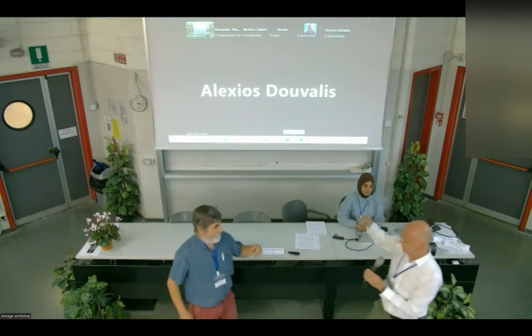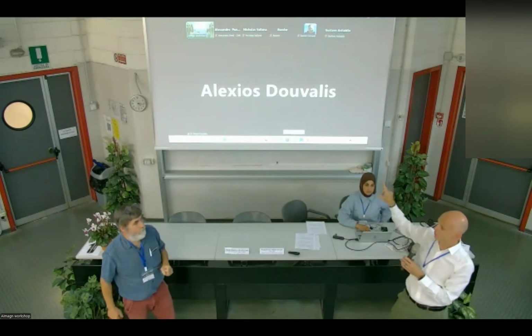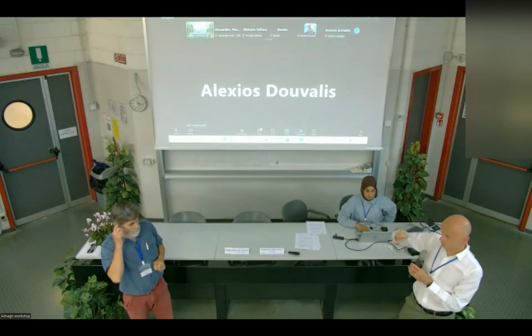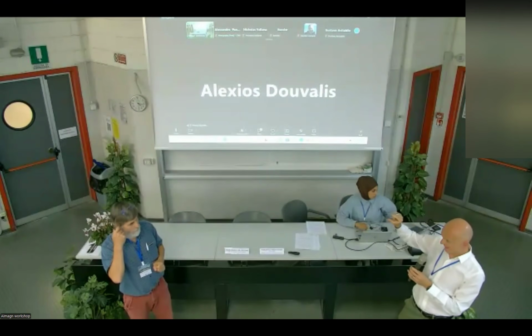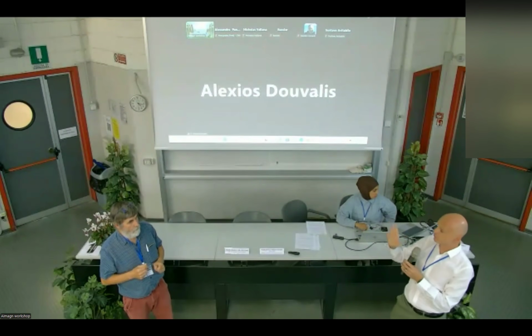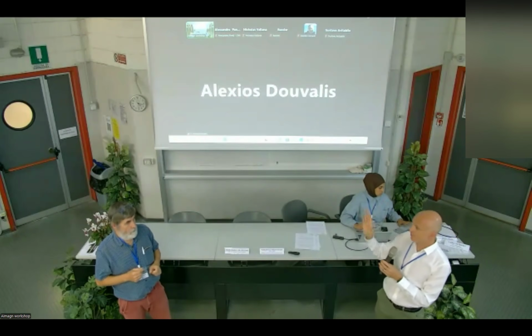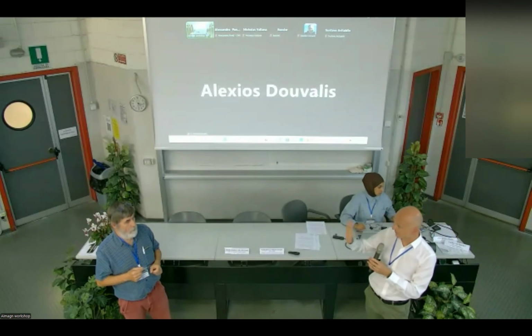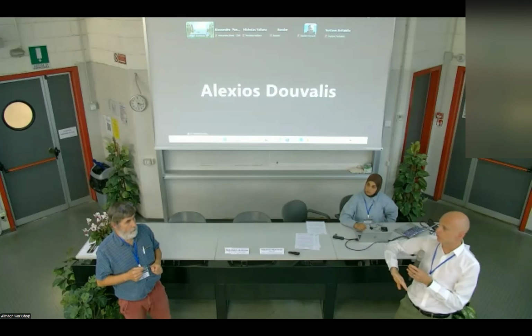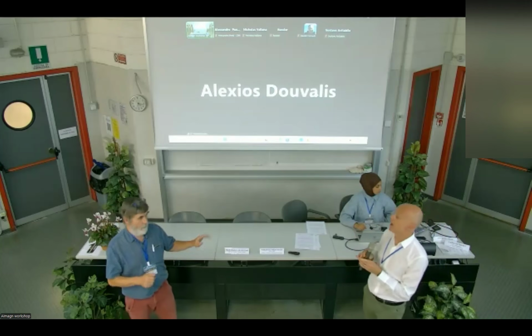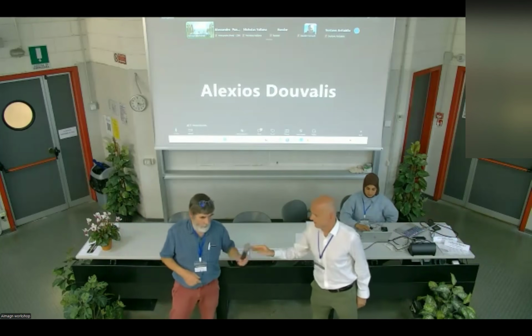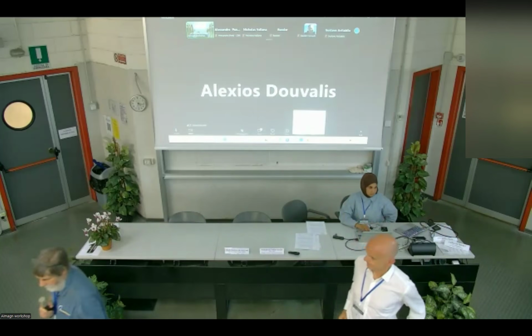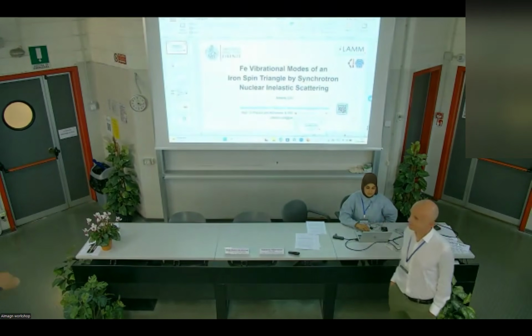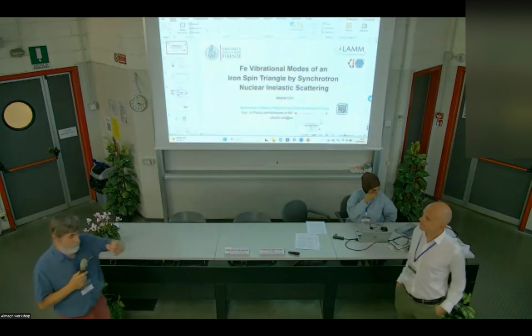If you are referring to the experiments with iron 57 on top of the topological insulator, it is all iron 57. To get information from the interface, that's the reason why I always use references. It was done by comparing different samples, but from the technique itself, from a single sample, you do not know from where it comes. Absolutely, it's integral.